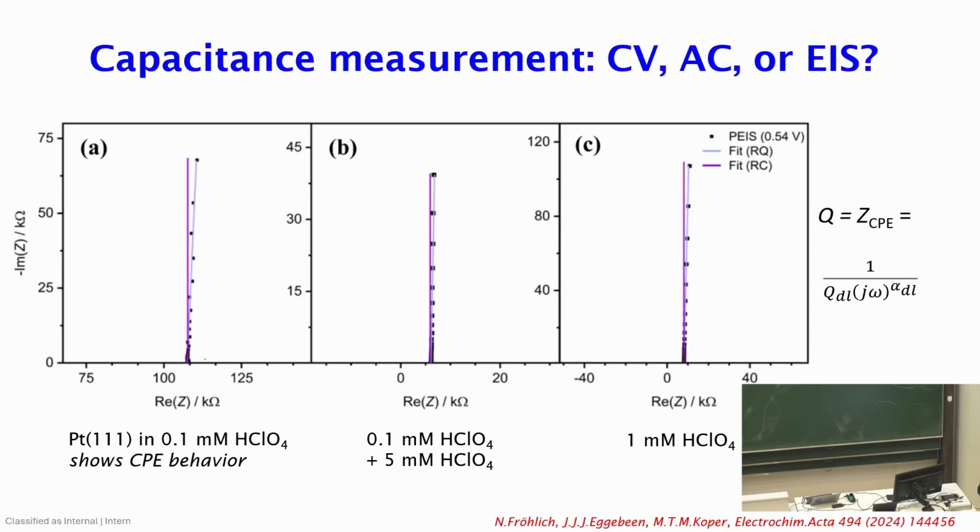In principle, they're right. But if you just have a simple capacitor, it shouldn't matter. You should get exactly the same number. So we finally did the experiment and we saw that it actually does matter. If we do the impedance, we get different numbers, but for a different reason. It turns out that what we thought was a perfect single crystal does not behave perfectly electrostatically.